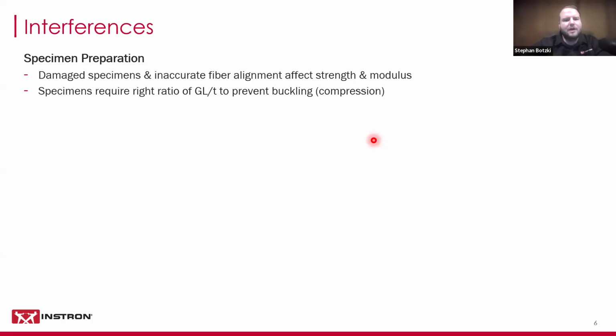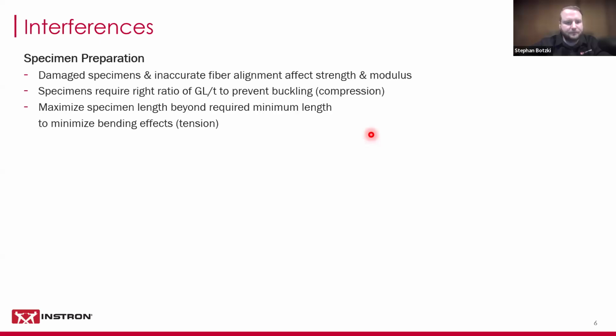You also need to have the right ratio of gauge length to thickness to prevent buckling in compression tests, for example. And again, testing standards give you good guidance on what ratios to use, or they have standardized specimens that are known to work well. So if you need to make adjustments to yours, then make sure that the ratio works. Otherwise, buckling will of course affect your strength and especially your strain and therefore modulus readings.